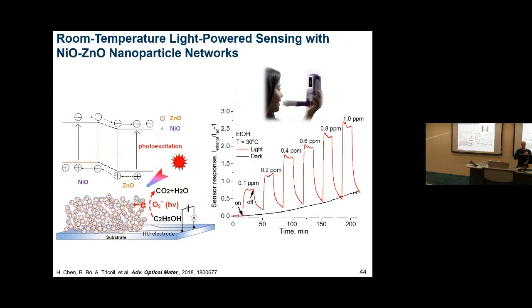The interaction will likely be interesting if you want to use this chemoresistive device at room temperature. This nickel zinc oxide nanoscale heterojunction, without light at room temperature, has no response to ethanol. But if you have light, you generate carriers, separate them at the heterojunction, and you can use them for sensing something like ethanol and other gases.